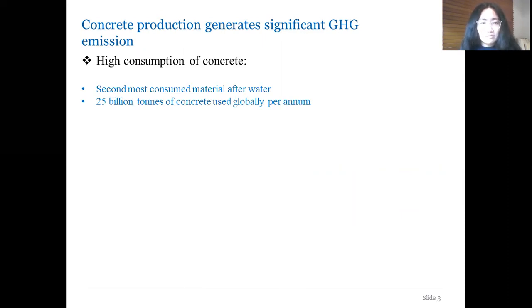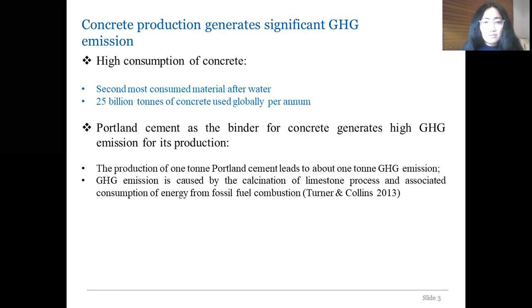To realize sustainable and low carbon infrastructures, we then need to look at where significant greenhouse gas emission or environmental problems were generated. And the research shows that one of the main causes would be the use of concrete. The concrete is the second most consumed material after water, and we consume 25 billion tons of concrete used globally every year. But the concrete is made from Portland cement as the binder, but the Portland cement production leads to high greenhouse gas emission. Producing 1 ton of Portland cement leads to about 1 ton greenhouse gas emission.